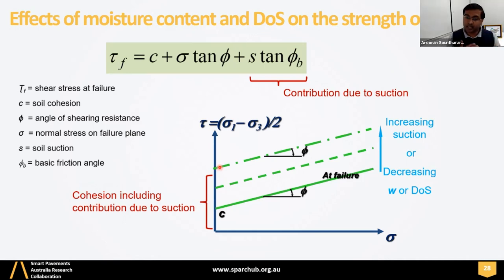Therefore, the pavement material becomes more stable and strengthened than the previous stage. Therefore, degree of saturation is an important parameter which contributes to the strength of the pavement, right? So if you control the degree of saturation very well in the pavement, you are always away from this failure line.